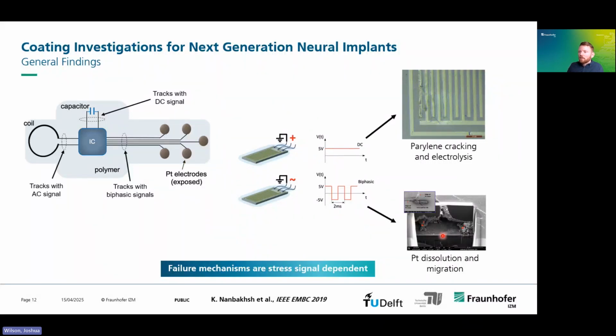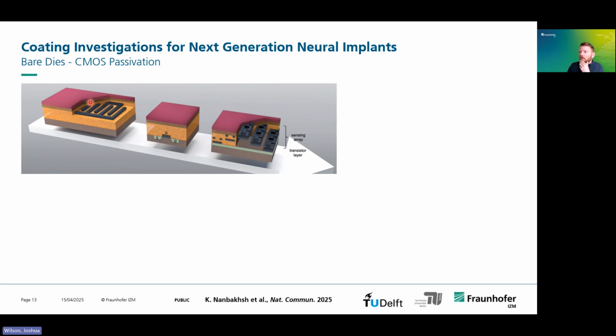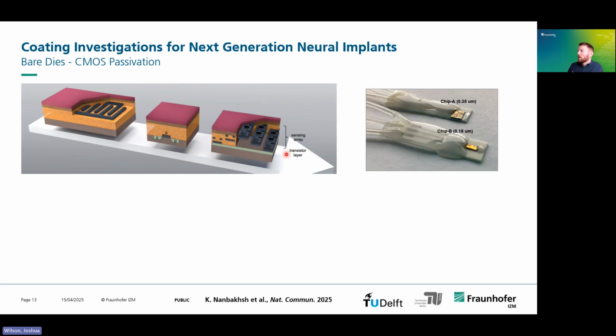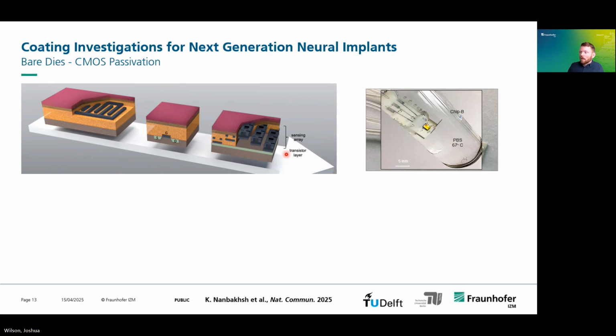And then based on this, we look at the IC, because the IC is the place with the highest electric field. And so potentially this is an area where the failure could be fastest. So we built some test structures inside an IC in different layers. We have some interdigitated capacitors, we have some transistors, we have some dielectric sensors, and we connected it up for soak testing. And we soak this at 67 degrees, so it's again accelerating the potential failure rate by increasing the temperature.